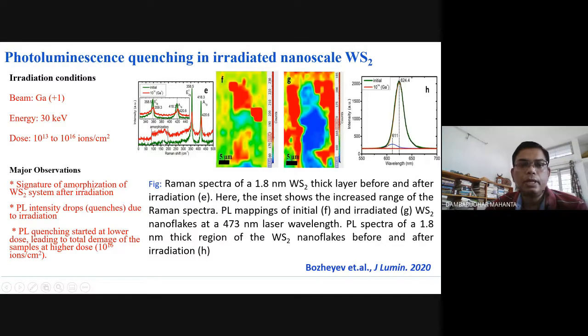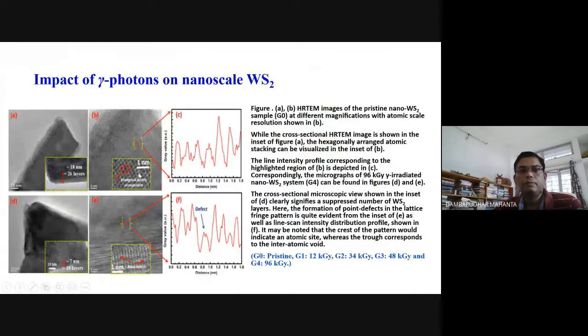So in this particular case, because of irradiation, you see there is a drastic change over here, along with a new peak, new evolution in this particular region. So these authors, they have ascribed this to amorphization of certain material. Amorphization means localized disorderedness has been introduced into the material. Now, impact of gamma photons on nanoscale WS2, this was by our group.